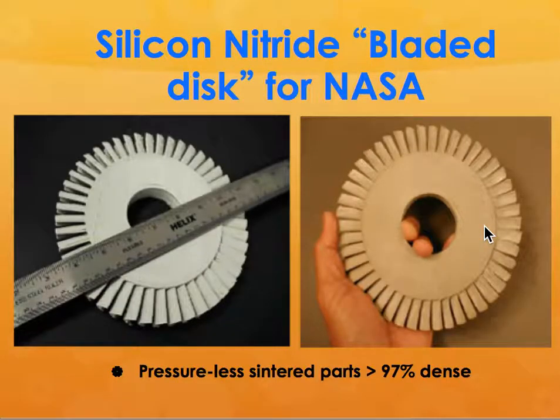Here is a silicon nitride bladed disc for NASA. This has something like 56 integral blades attached to a solid inner ring. You build it during the actual process itself. To build it took us something like 64 to 96 hours, done almost non-stop. Then you had to debind it, which took another 96 hours, and then sintering, which took something like another 72 hours.